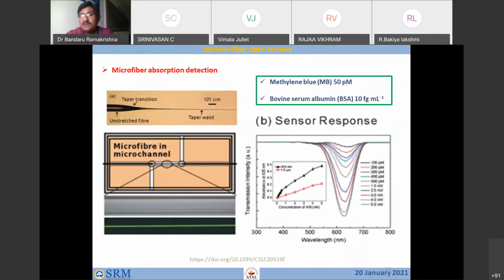In the second modality, people tried with absorption. For example, if you have a molecule which has absorption characteristics, which eats the light, for example methylene blue absorbs a particular light. The moment this molecule comes in contact with the fiber, the particular light will be absorbed by this molecule, so that in your spectrometer, that light will disappear. That particular wavelength of light will be disappearing. How much of the molecule is binding, that much light at the particular wavelength will be reduced. So you can calibrate again and find out what the concentration could be. People have tried with bovine serum albumin and methylene blue.